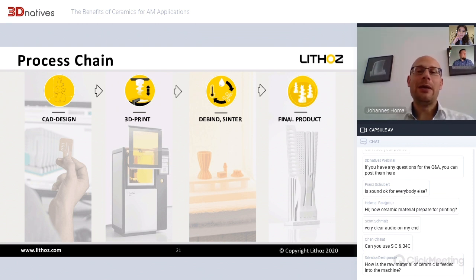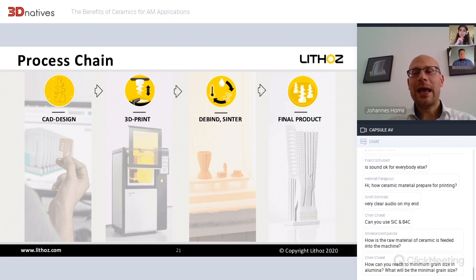The big difference between most other 3D printing processes is that we have here a two-stage process. As with every AM process, we start with a CAD design and then we print the part. But in ceramic processing, we have then just achieved a so-called green part. This is just a composite of the binder and the ceramic particles, and then they have to undergo a heat treatment. Basically, we have to bake them to achieve the final density. This means we have to debind the binder, burn off the binder, and then sinter the ceramic to full density, and only then do we have these ceramic properties and the final product.